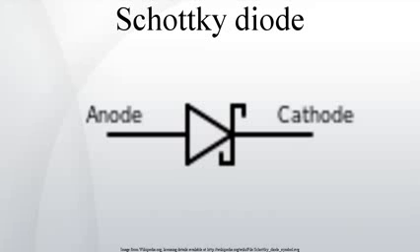Silicon carbide has a high thermal conductivity, and temperature has little influence on its switching and thermal characteristics. With special packaging, silicon carbide Schottky diodes can operate at junction temperatures of over 500 kelvins, about 200 degC, which allows passive radiative cooling in aerospace applications.